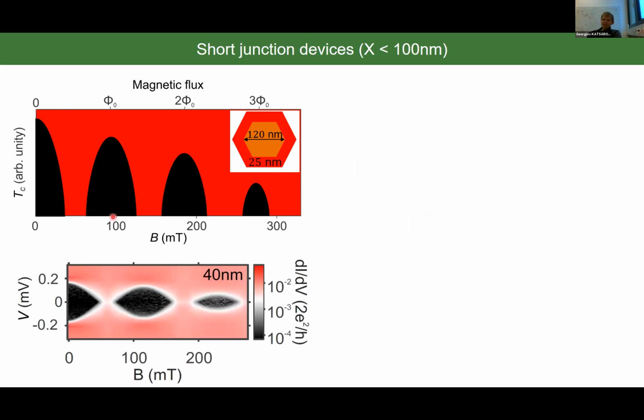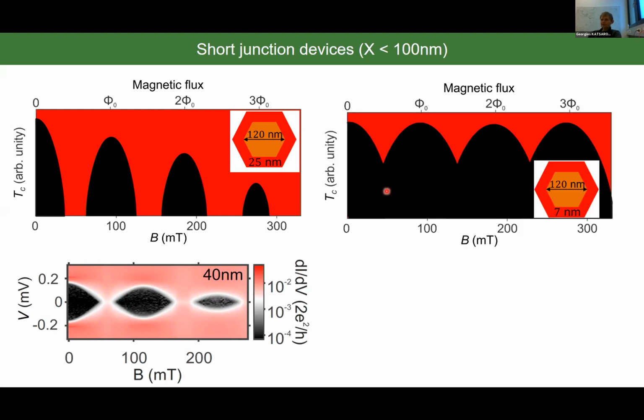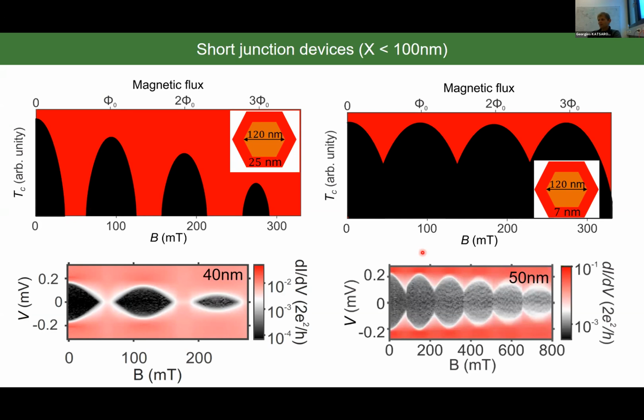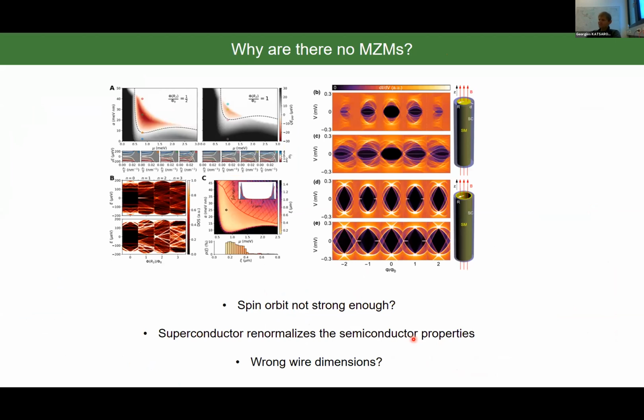However, all the devices we have been studying were in the destructive Little-Parks regime. So could it be that in order to see Majorana zero modes, we need to go to the weak Little-Parks regime? So practically, if you shrink the thickness of your superconductor quite a bit, you will end up in a regime where superconductivity never gets completely destroyed. We fabricated also devices of this type. And here I show you just one measurement in the weak Little-Parks regime, where now the junction length is 50 nanometers, differential conductance versus bias and magnetic field, beautiful weak Little-Parks regime, but no zero bias peak. So then the question is, why don't we see Majoranas?